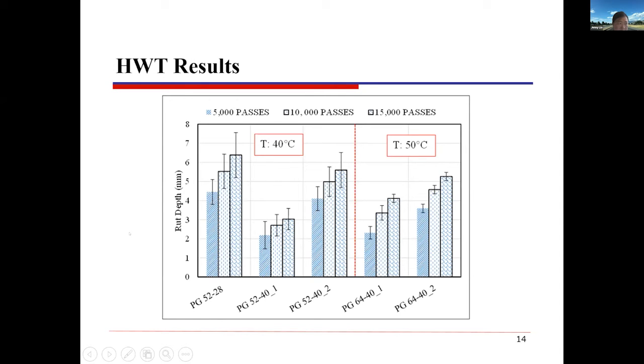And this is the Hamburg wheel tracking test results for mixtures. You can see the use of HPABs improved the rutting resistance at a noticeable level, regardless of the high-end PG of the asphalt binders. And so we see mixtures with unmodified asphalt binder show higher rut depths than those with modified asphalt binders.